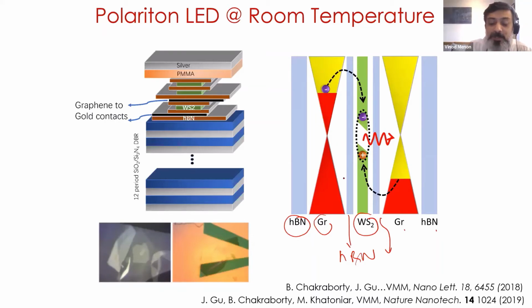You have graphene, you can apply a gate voltage, you can change the Fermi level, and so now you can make your Fermi level above the conduction band of the tungsten disulfide. You can make it here below the valence band of tungsten disulfide. So now you can inject electrons here, you can inject holes here, and the electron and the hole will recombine in the system and emit a photon. So it's an electrically driven device.